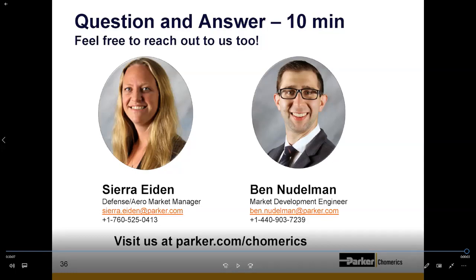We have a question from Jeff about the relationship between a conductive elastomer's DC resistivity and its shielding effectiveness. That's actually a great question and an important nuance. While there are some materials we've developed, for example our nickel-plated aluminum, that provide the highest shielding effectiveness at various frequency ranges, they actually have a relatively high resistance, or DC resistivity, which means a lot of the time they won't meet low contact resistance requirements.